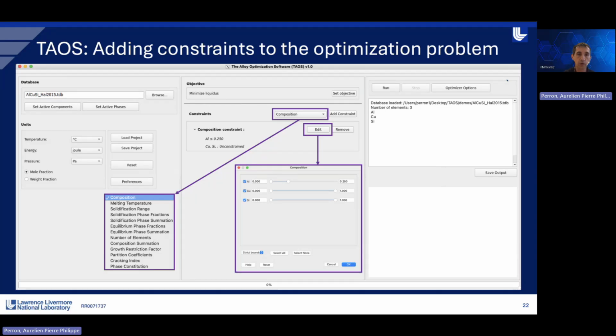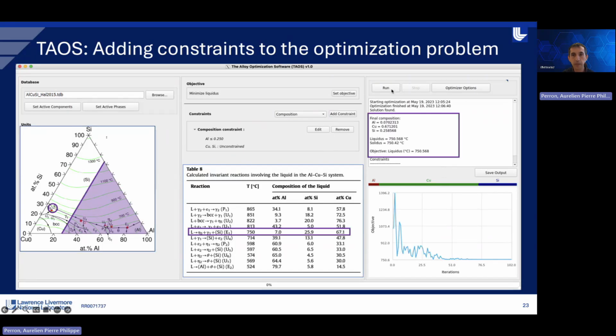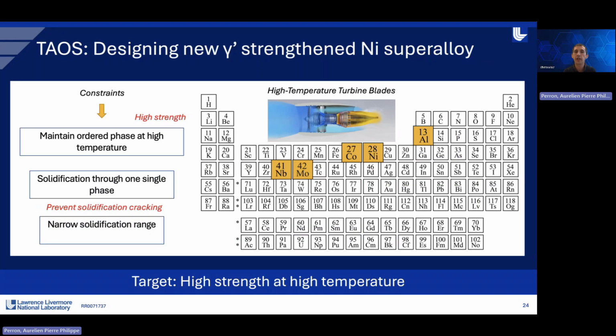The main difference for the constraint here is that if you look at the composition, now you can play with the ranges. So in that example, we want to have aluminum between 0 and a maximum of 25 atomic percent content. So that's what we selected. And then you can, again, run the optimization. You will have the results, and you can double check with the literature that the results match. So this was, I would say, a fairly simple example to highlight how TAOS works.